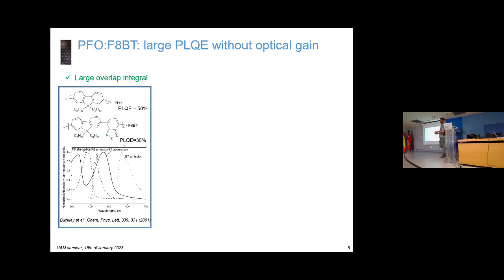At this point, I will get into the matter. These are basically the two main characters of the story I'm going to tell you. This is called polyfluorene. For people working in semiconducting polymers or optoelectronics, it's a very well-known polymer because it can be processed into thin films with very high optical quality, and it's a quite decent light-emitting material in solid state. You can get efficiencies up to 50%. You can also functionalize it with other groups—for instance, you can include a benzothiadiazole on the backbone, which shifts the emission from blue to yellow. The quantum efficiency isn't as good as PFO, but it's okay.